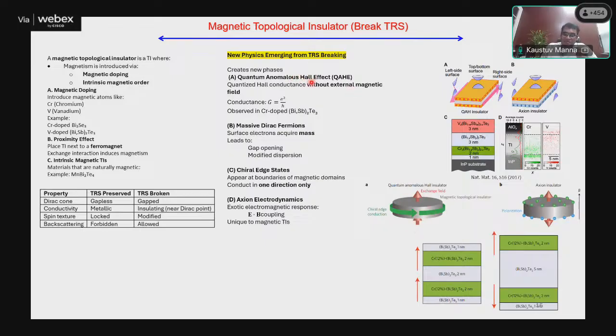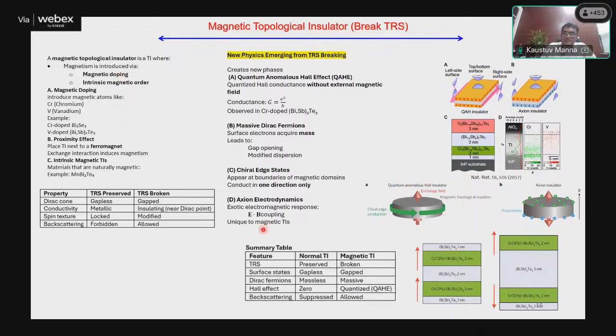Okay. So the axion insulator and the quantum anomalous Hall effect are both satisfied by manipulating this magnetic topological insulator. This is a comparison I have made: how different states you can observe in a normal topological insulator compared to the magnetic topological insulator. Time reversal symmetry is of course preserved for a normal topological insulator, whereas by inducing magnetism, you break the time reversal symmetry. Then the surface state is gapless in a normal topological insulator, whereas in a magnetic topological insulator surface states can be gapped out. It can be either one channel or both channels gapping out.